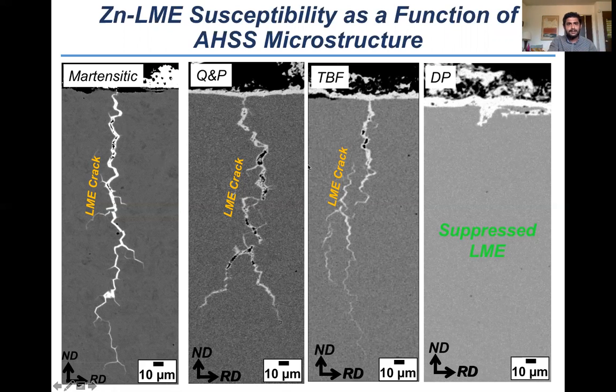It's very interesting because the martensitic QNP and TBF steels had very different starting microstructures, but yet they formed these LME cracks, which means neither the presence of retained austenite in the QNP steel nor the presence of bainite in the TBF steel affected the LME sensitivity of the QNP or the TBF steels. In contrast, the dual phase steel with a microstructure of ferrite and martensite does not form LME cracks. So it is a very important thing to note.